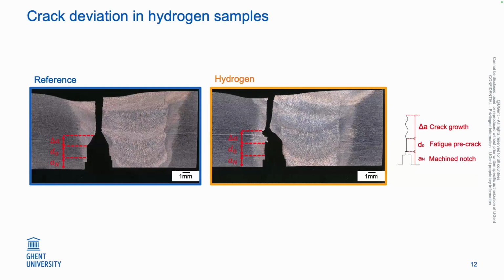And of course, since we're dealing with a heterogeneous specimen where we have the weld, the heat-affected zone, and the base material, we wanted to see how the crack evolves during the test. And also there, we focus on the crack paths. What is remarkable is that we have a crack deviation in the hydrogen specimen. So the crack deviates away from the weld and goes through the base material.